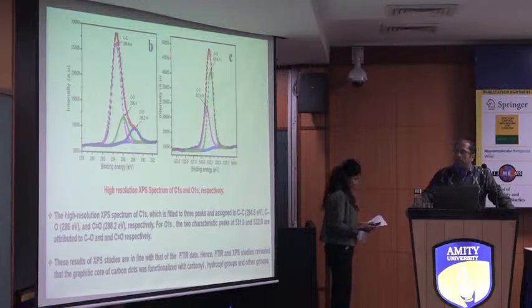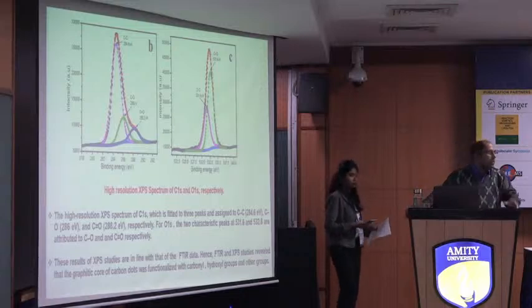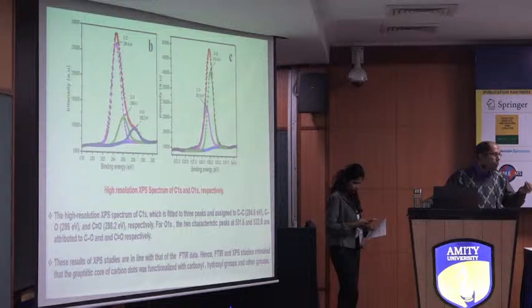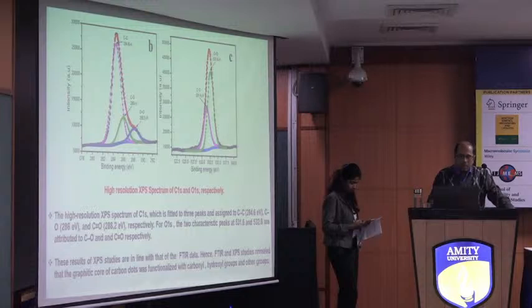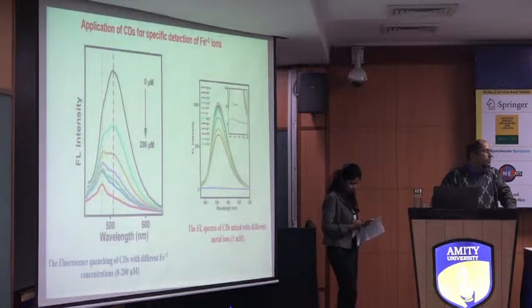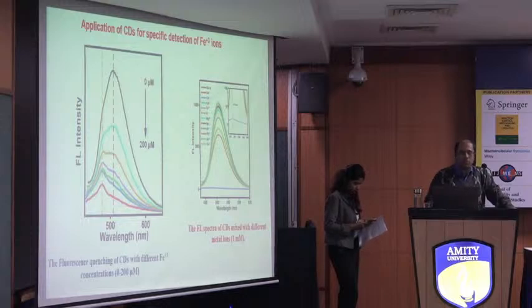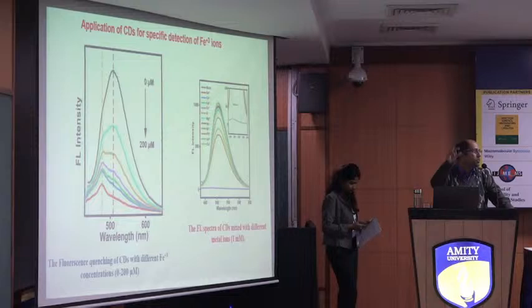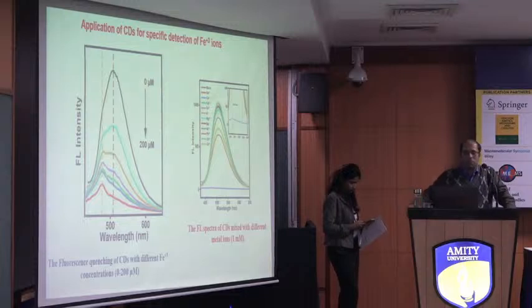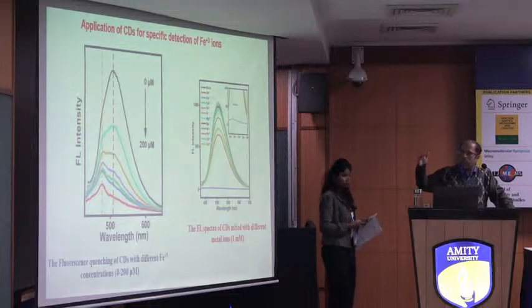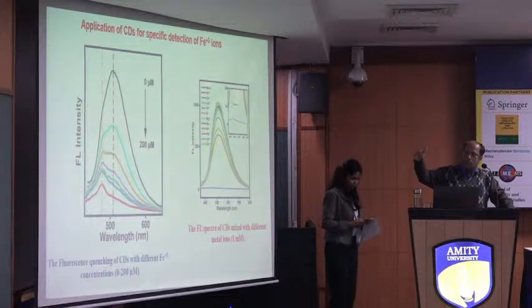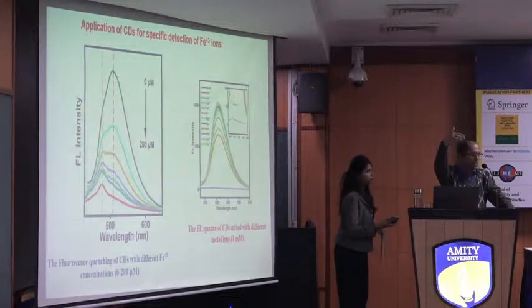Hence FTIR and XPS studies together reveal that our carbon dots consist of a graphitic core, which is functionalized with carbonyl and hydroxyl groups from the aloe vera. Now, as an application of the carbon nanodots, we used them for the specific detection of Fe3+ ions. For that, we took the carbon nanodots and mixed them with different concentrations of Fe3+ ions ranging from 0 to 200 micromolar, in the order 0, 25, 50, 75, and so on.